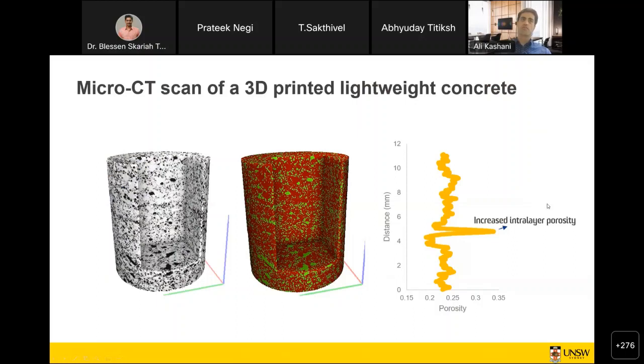And also another project using the micro-CT scan, where we printed lightweight concrete and put the samples in the micro-CT scan. As you can see, there are gaps between, so these are 2 layers actually, and you can see that there is very high interlayer porosity, and this is very important, especially when we put reinforcement between the layers. So any reinforcement, especially steel reinforcement, is going to be prone to corrosion because of the much better access to the steel, and the cover is not that good in 3D printing. So these are the things that we need to think about when we are talking about steel reinforced 3D printed concrete.